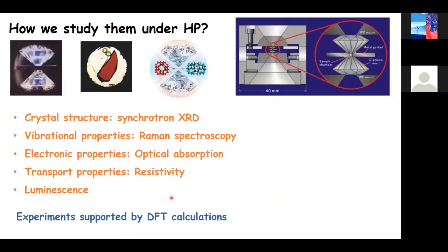So then how do we study them? Those who are experts in high pressure know that everybody uses for doing these studies the so-called diamond anvil cell, which basically, for those not familiar with it, is just two diamonds which have the culets facing each other. In the middle, we put a metallic gasket where we drill a little micron-sized hole, where we will put our sample. Could be a crystal or a powder. A pressure standard, in this case a ruby ball, which will determine the pressure, and the pressure medium that will guarantee the quasi-hydrostatic conditions.